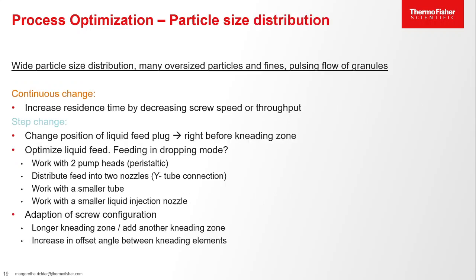Another example, if we talk about the particle size distribution: if you have a very wide distribution and many oversized particles and fines and also a pulsing flow of the granules, what can I do about it? Well, in this case, it makes sense to increase the residence time. So you can imagine if you increase the residence time, the granules have more time for the granulation, you have a bit more back mixing effect, and this will make the system more consistent. You can do this by decreasing the screw speed or the throughput. Both things will lead to a longer residence time.